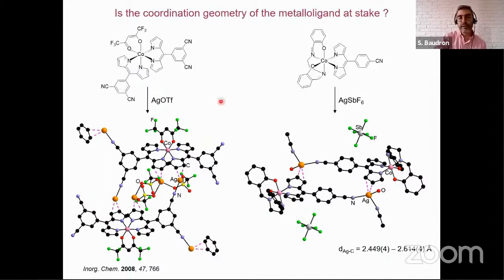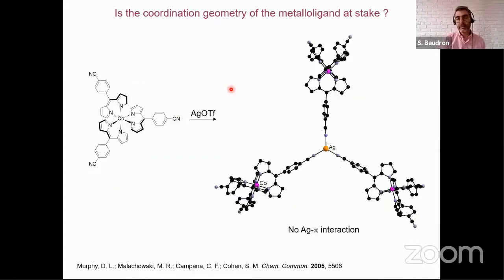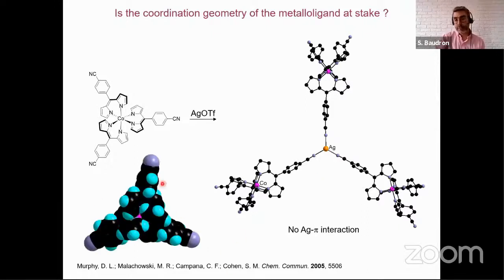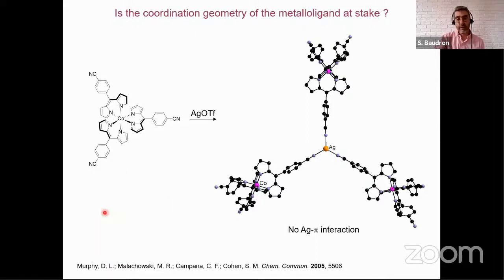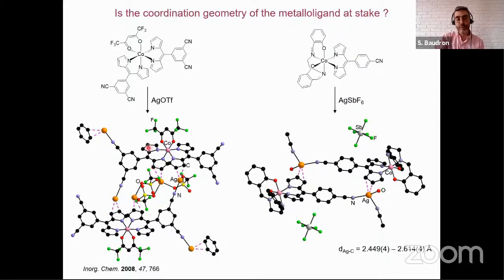So it is interesting to note that in this case we do have this interaction, even though this is with an octahedral cobalt complex, because as I mentioned before, the group of Cohen has elegantly studied the assembly of homoleptic cobalt complexes with silver 1 cation, as shown here with the same ligand as the one we've just described. And in this case, they have no silver-pi interaction in their crystal structures. So this was rather surprising to us. Maybe it's because of the geometrical organization of the pyrrolic system around the metal. You see here a rather regular coordination sphere, while in the case of our heteroleptic system, this is much more open. You have here sort of a distortion around, although the coordination geometry is really octahedral around the cobalt cation.